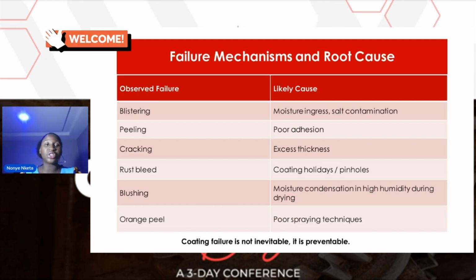Then blushing. Amine blush, for epoxy based coatings, comes up mostly when you're coating under moisture or a high humidity environment during drying. So you want to cure a product that is not supposed to cure under moisture. You want to cure it while the relative humidity is high. You definitely get that blushing. You start seeing a lot of shades on a surface that has been coated. Then orange peel, that is also as a result of poor spraying technique.